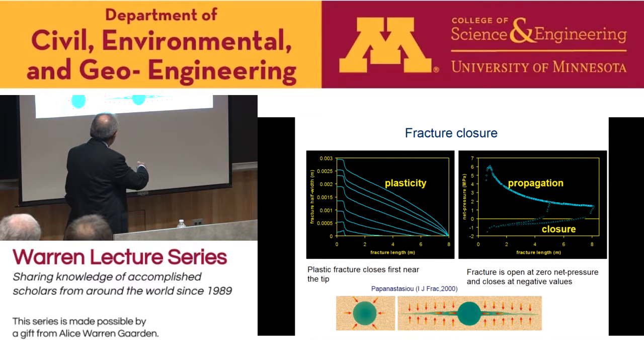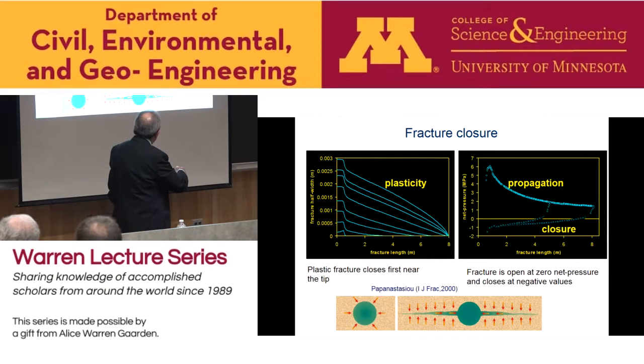In this case, with plasticity, we see that the fracture closes initially everywhere, just from the relief of the stresses in the process zone, and then it closes first near the fracture tip, as you can see from here, and last near the wellbore. And if we look at the pressure versus time, this is during propagation, and then during closure, we allow it to close after we reach this value here. It drops rapidly, and then it will close here at negative net pressures.